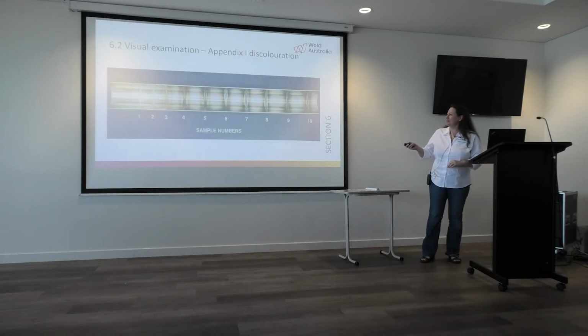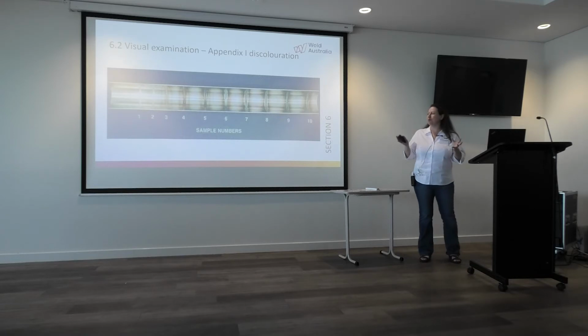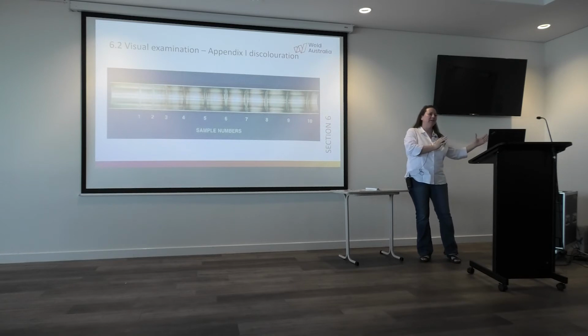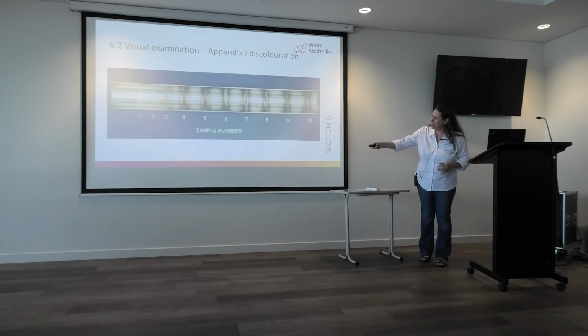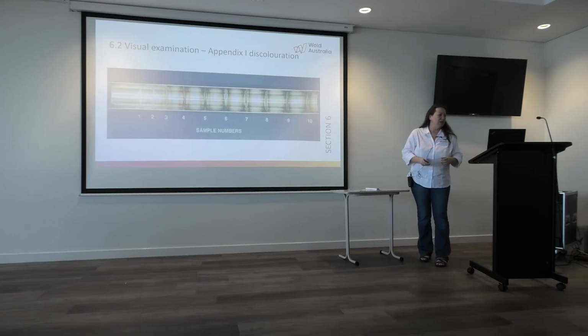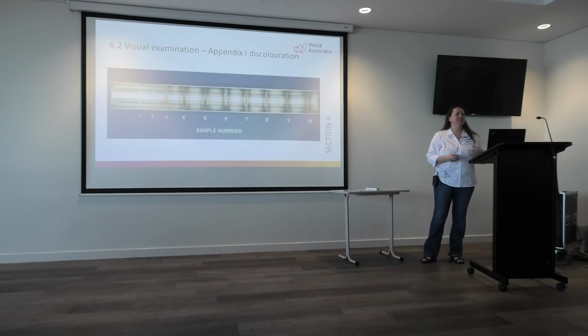And this is the slide I was excited to share. This is what it comes in with Peter in terms of, and the question also that was there for pickling and passivating on site. Appendix I was added to accommodate what do we do with site welding. So you've got two ways of dealing with stainless steel in terms of whether for service to make sure that it meets the requirements. Either you have some effort before welding or you have some effort after welding. So you don't have to pickle and passivate if you can meet requirement number 1 and 2, and in some applications 3, which is your residual oxygen content in your backing gas.